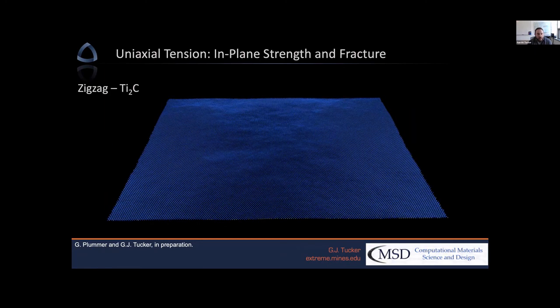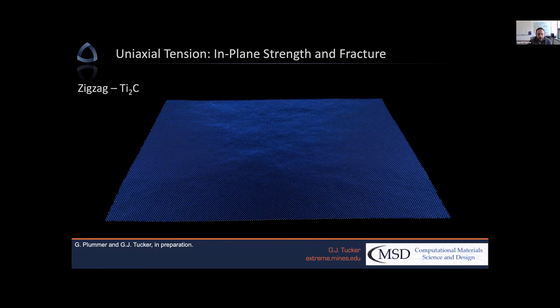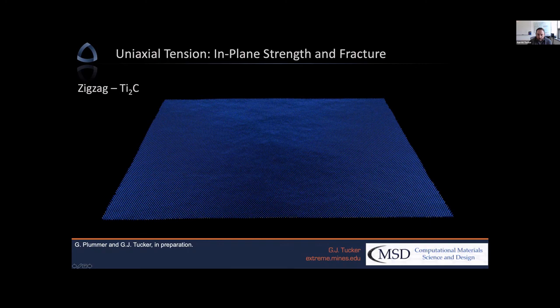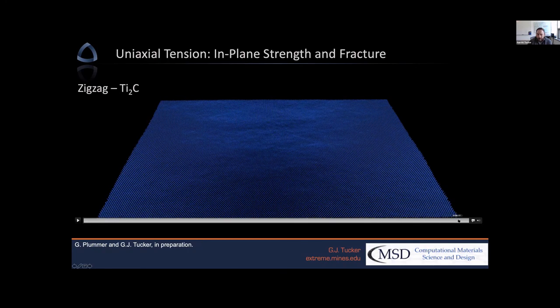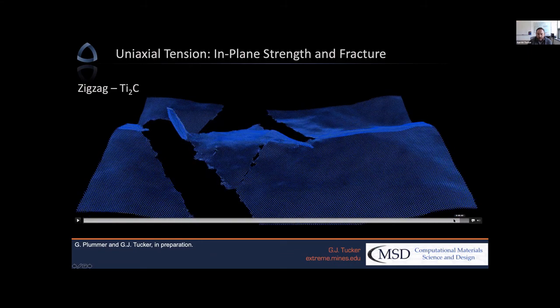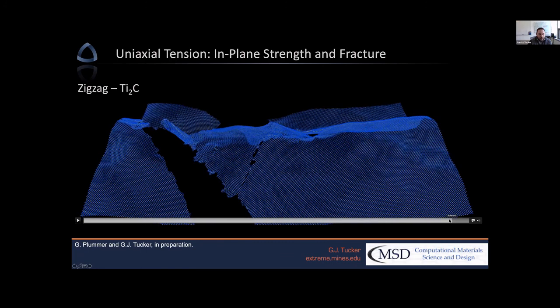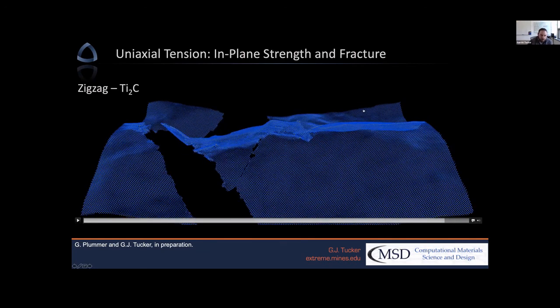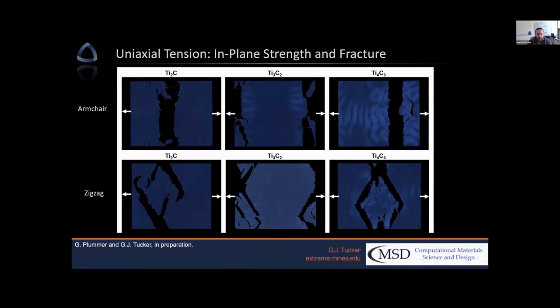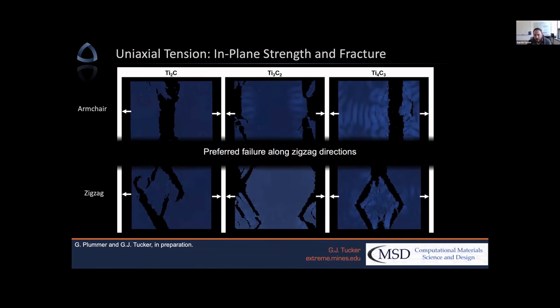But here now we do the zigzag direction, and this is another Ti2C simulation. And I'm going to speed it up here to where it breaks. And here we get a completely different type of fracture path. So not only are the in-plane values that we calculated earlier different, but the behavior of fracture in plane is completely different as we change the orientation. And here's a comparison looking at the 3 different stoichiometries, comparing armchair and zigzag. And one of the consistent themes here is that we see this preferred failure along the zigzag directions. And like I said before, these are pristine, bare MXenes right now. Now adding surface terminations and these defect configurations are underway right now. And so we can't comment on those results, but they do obviously influence the fracture behavior.